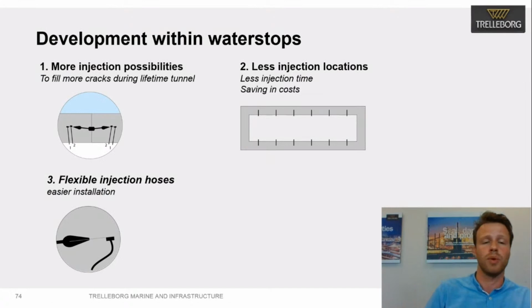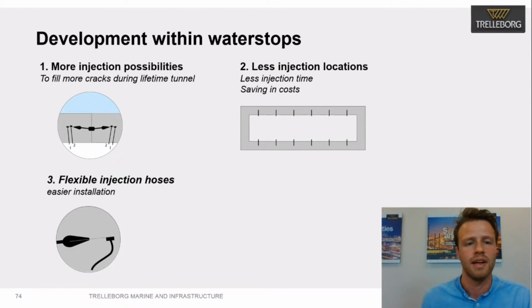We are currently developing our Waterstops because, as I already mentioned, there are some difficulties with the injection possibilities. One of the developments we are working on is the implementation of more injection possibilities. You can imagine if you pour in a certain amount of resin at the beginning of your tunnel lifetime, you might encounter cracks later on. So we want to provide the extra opportunity to inject an amount of resin within the Waterstop, for example, after 20, 30 years. Another thing we want to take into account is flexible injection hoses, because the current systems are rather static and difficult to handle. If we could change that to a flexible option, it would be way more workable and make the installation easier. Also, fewer injection locations would be beneficial, as it would save cost and limit the injection time, which is obviously something that would be needed and wanted.